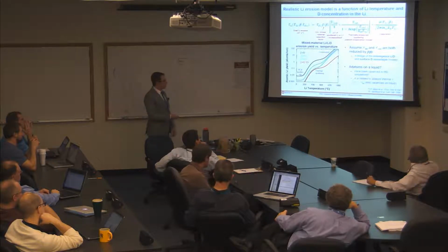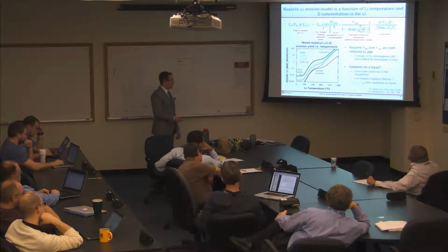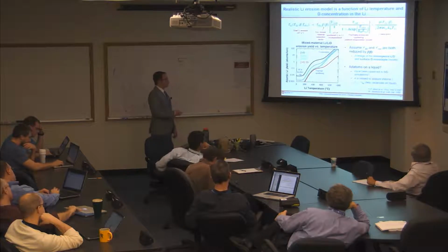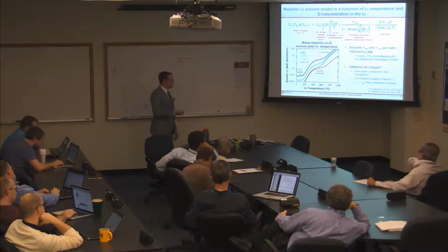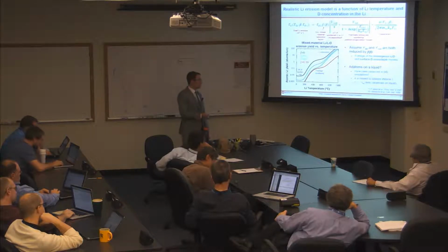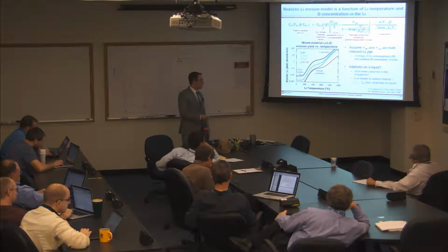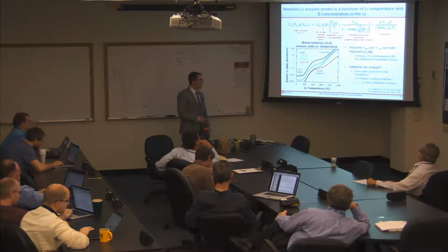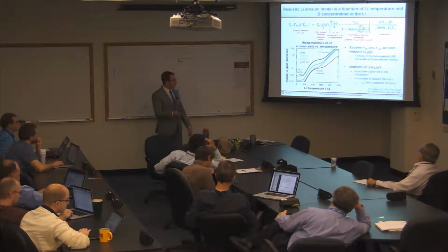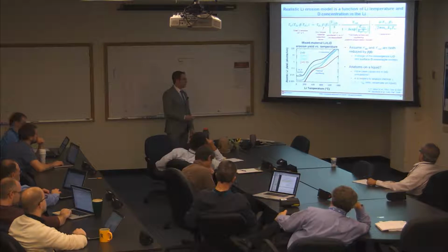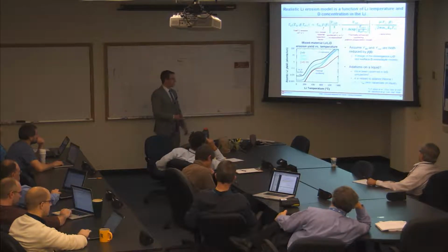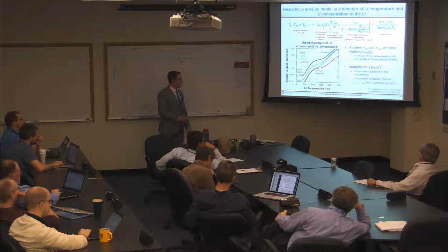The formulation of a model with liquid adatoms is a bit unorthodox, but they have actually been observed before in molecular dynamics simulations. This A parameter is related to the lifetime of an adatom on the surface, which is basically how long it spends diffusing around the surface before it recombines or sublimates off. If you calculate it, you find that the tau for lithium is much greater than for solid beryllium. This makes sense, because you would expect that a lithium adatom would have to diffuse around a very long time on a liquid surface to find a vacancy, versus a solid surface where there would be a lot more vacancies. So you would expect the lifetime to be a lot longer.